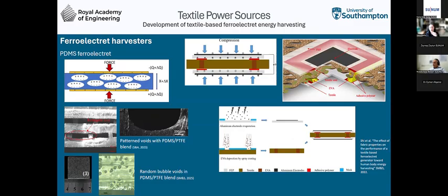Another mechanical energy harvesting approach we've looked at is a device called a ferroelectret. An electret is a well-known, typically polymer, material that is able to store charge at the surface. It holds that charge for a very, very long period of time, indefinitely, if the conditions are right. And in a ferroelectret, basically we introduce voids within that polymer material such that the charge is stored across the surfaces of the voids.